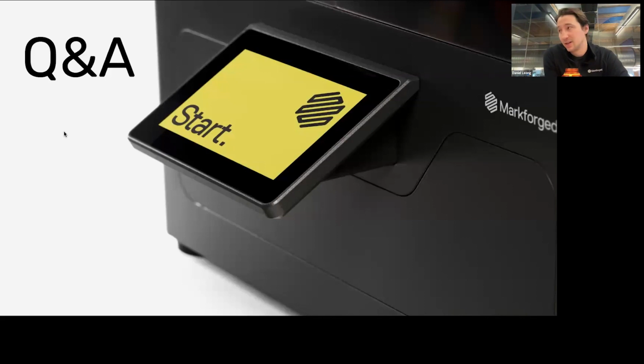That being said, our typical parts have voids on the inside of them. We print with open cell infill. The result is that shear strength is fundamentally weaker than pull strength, because there's less surface area between the parts when you're printing with that infill. Likewise, the density of final parts is not anywhere close to 95%. I call it design porosity. You have porosity in the center of the part. Depending on your part size, you can absolutely print solid, and that kind of solves the two problems and gets you much closer to your base spec. But most parts we print don't adhere to that.